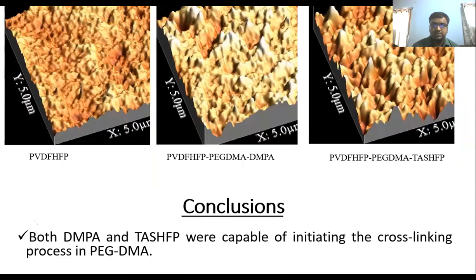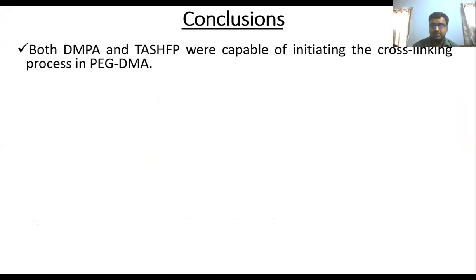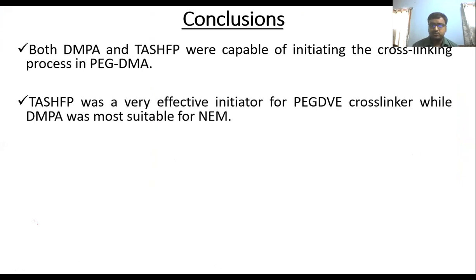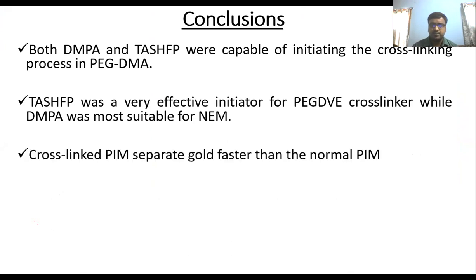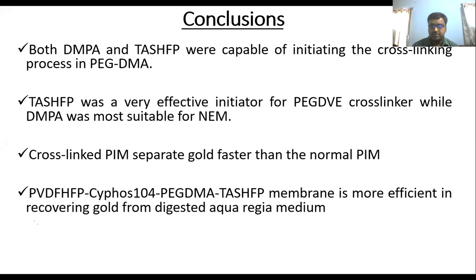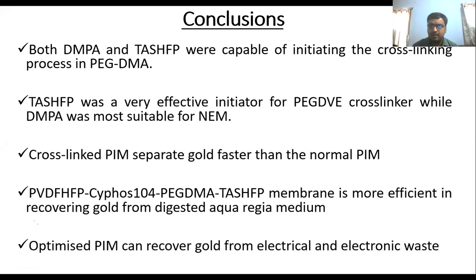So with all this, I'll conclude that both DMPA and TASHFP are capable of initiating the cross-linking. DAS-HP is a very effective initiator for the cross-linker, while DMP was most suitable for the methacrylamide. The cross-linked PIMs separate gold faster than the normal membrane. And this composition, with PVDFHFP-Cyphos104-PEGDMA-TASHFP, was most efficient for recovering gold from digested aqua regia. And the optimized system can recover gold from electronic waste.